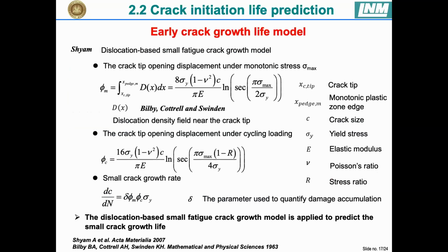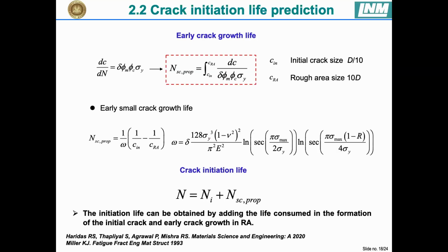And for the early crack growth life model, we adopt Shyam's dislocation-based small fatigue crack growth model. The crack tip opening displacement can be obtained by integration of the dislocation density field function proposed by the BCS model. And then by integration from the initial crack size to the rough area size, we can get the early crack growth life. And then the total life can be obtained by adding the life consumed in the formation of the initial crack and the early crack growth in the rough area.